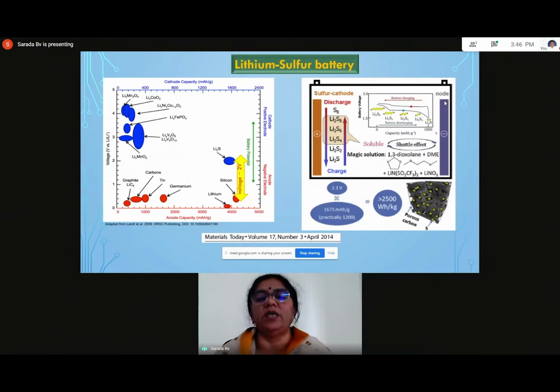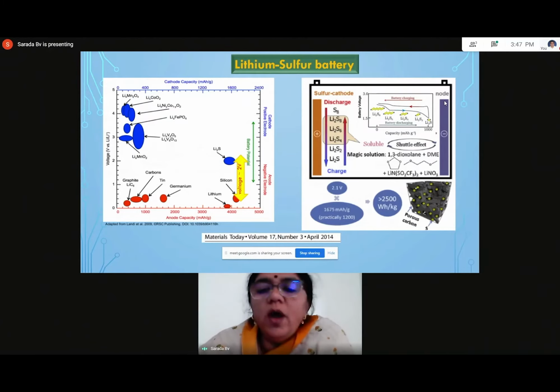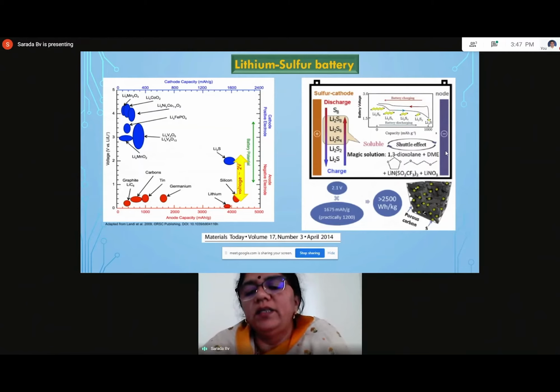But practically, the problem is that during discharge, several intermediate polysulfides are formed during the lithiation, that is the discharge process, at different potentials, and they get dissolved into the electrolyte, and ultimately for the second cycle there is a lot of decrease in the output. This is called the shuttle effect. In order to decrease this, you have to engineer. You already know sulfur is a good cathode, and you already know that it is facing these problems. So the next important part is to engineer the cathode.